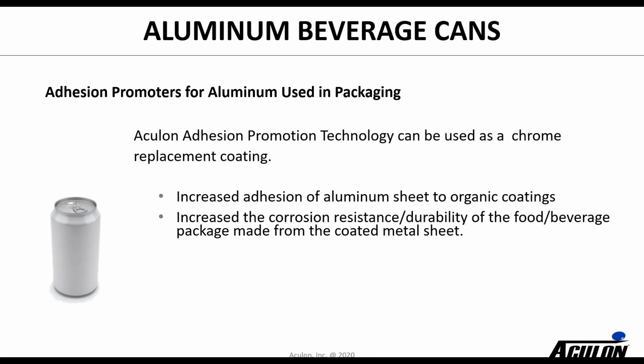So with aluminum, we can apply our full range of adhesion promoters. One of the pushes in the industry is to try to get away from some of the chrome coatings, and we've been able to show that we can improve the adhesion of the beverage can liner to the aluminum, and so that's of course a big market.